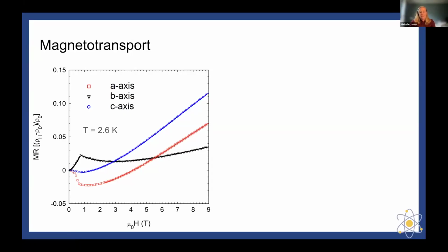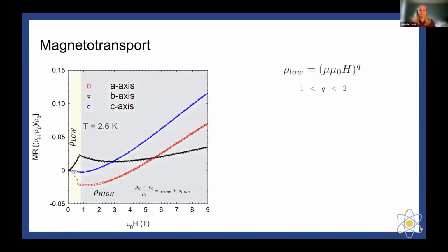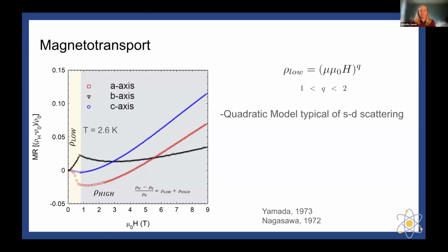So 0.75 Tesla is right where we have that spin reorientation along the A and the B axis, which persists throughout temperature. So we analyzed the data looking at the resistivity in the low field and in the high field. In the low field, we used a mu times (mu naught H) to the q power, where mu naught H is just the applied field and q is between 1 and 2. So you can kind of think about this as a quadratic-based model that's slightly different from the higher field data. We use the quadratic model, which is typical of SD scattering in the electronic orbitals.